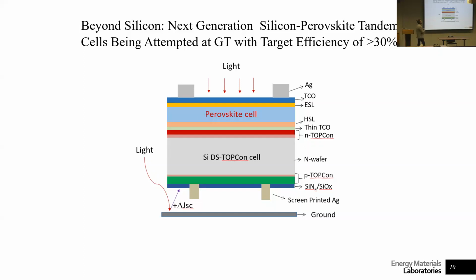And not only that, but we can also change their band gap. We can make the band gap be 1.5 or 2 or 3 electron volts, and that gives us a lot of flexibility with engineering of this top cell. Why it matters is because the silicon solar cell has a 1.1 electron volt band gap that is fixed, and it is very hard to change. Actually, I would say nobody has even tried to change the band gap because it's not possible by having just silicon material. You would have to go into maybe some alloys or some compositional changes.